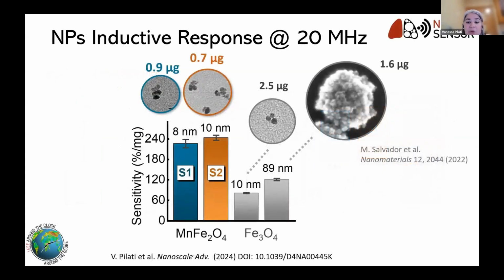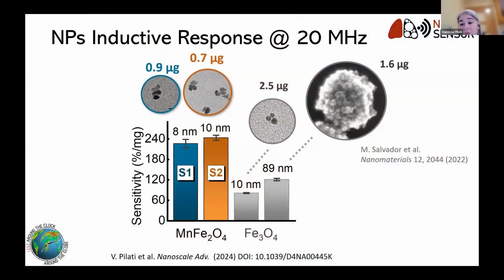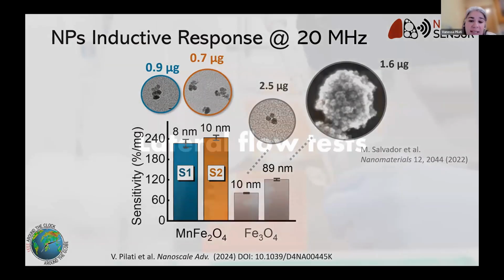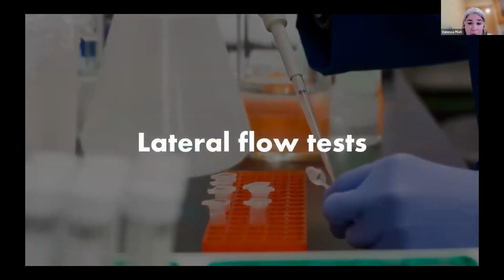We here compare two different magnetite nanoparticles. They are most used in the magnetic lateral flow assays, and we can see that for the case of 10 nanometers, they were synthesized using the same chemical route. They have the same size, and we can see that we have three times the sensitivity in comparison to the magnetites. And we also compare to our previous best results using magnetite nanoclusters, and the sensitivity is twice just by using manganese ferrite nanoparticles.